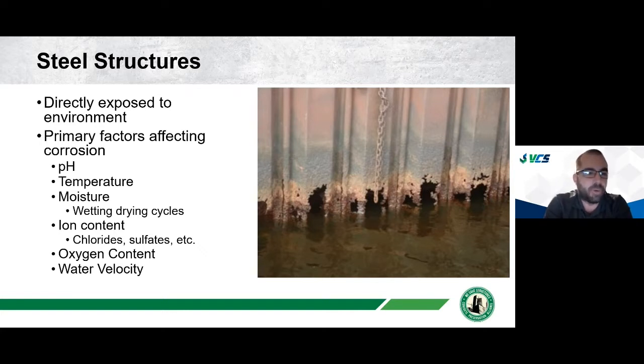With regards to the water, obviously we need to understand the chloride and sulfate content of that water, because now we're directly exposing it to the steel. The wetting drying cycle, so the tidal, you can kind of see the image here. We're often going to see the most severe damage in the tidal splash zone. So how high those tidal ranges are will affect the worst zone of corrosion activity.